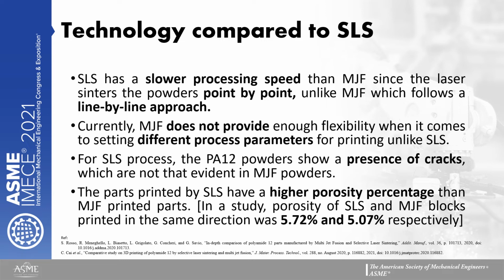Multi-jet fusion technology comparison to SLS. SLS has a slower processing speed than MJF since the laser sinters the powder point by point, unlike MJF, which follows a line-by-line approach. Currently, MJF does not provide enough flexibility when it comes to setting different process parameters for printing, unlike SLS. For the SLS process, the PA12 powders show a presence of cracks, which are not that evident in MJF powders.